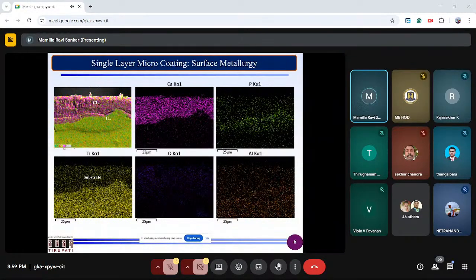So what you can do here is area elemental mapping. Once you map the complete surface area, CL stands for coating layer and TL stands for transition layer. Then you can check how the elements are stacked. As I said, I have used titanium material, and on top of it I have used calcium phosphate-based orthopedic materials. What I'm showing here are the pink particles. Once I do all the elemental mapping, you can tell where the calcium particles are, where the titanium particles are, where the substrate material is, and the oxygen.